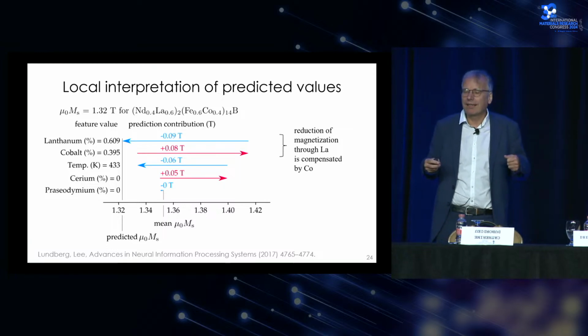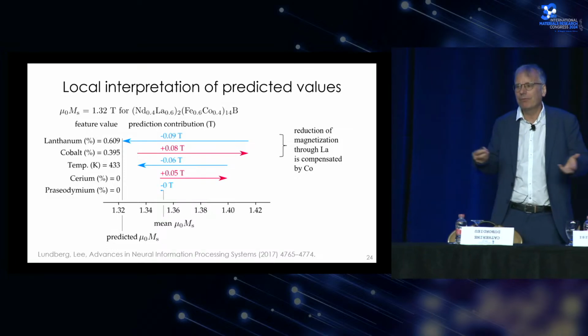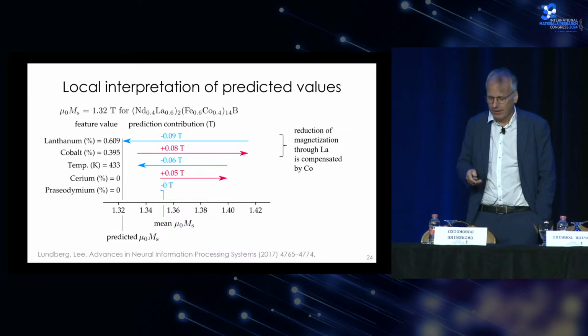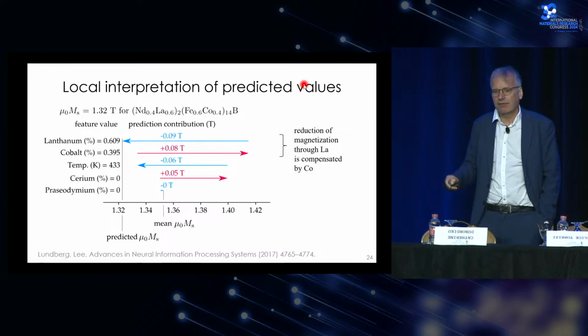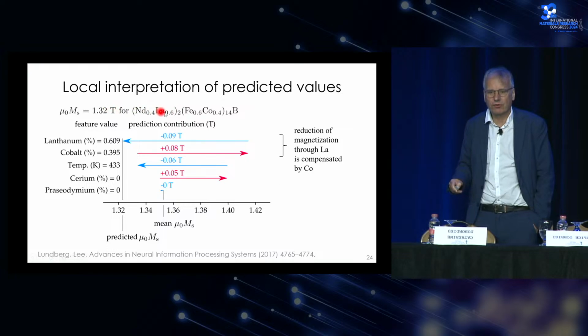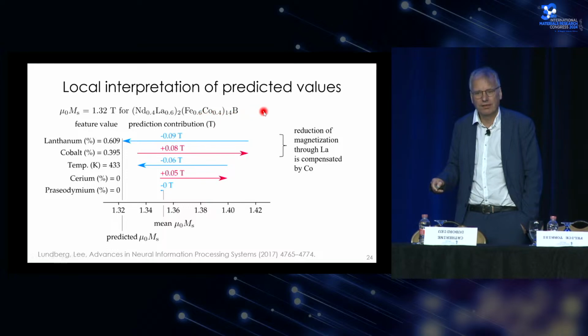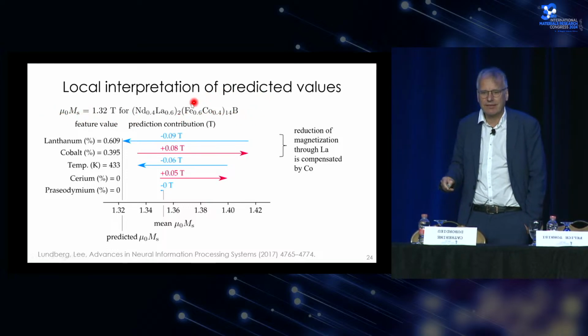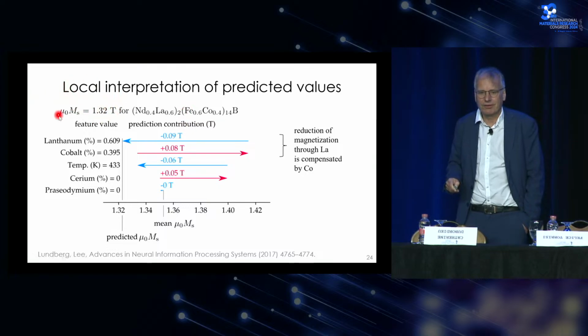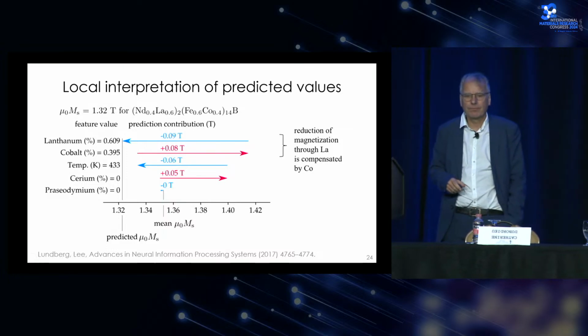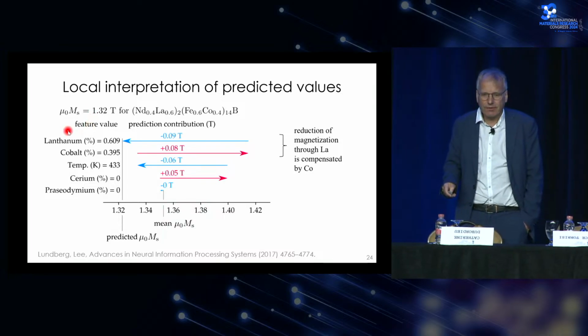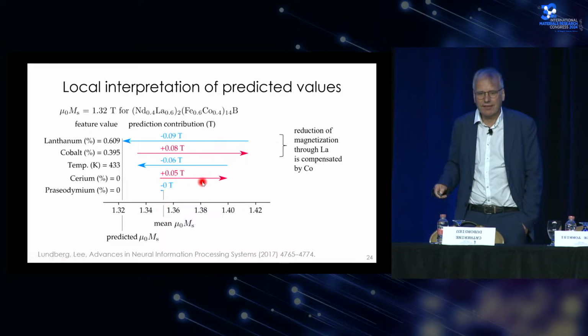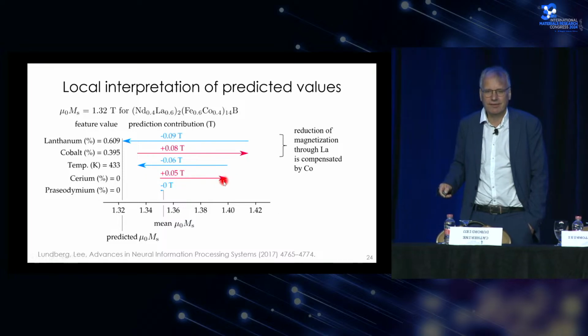But we can do much more. We can help to understand why we observe a certain property by use of machine learning. So we can interpret the predicted values. For example, we look at a certain chemical composition, neodymium 0.4, lanthanum 0.6, then iron 0.6, cobalt 0.4, and boron. We see this composition has a certain magnetization of 1.32 Tesla. By using the machine learning analysis, we know that in all our data set, the mean magnetization is at this value here. Because we don't have any cerium here, we increase the magnetization.